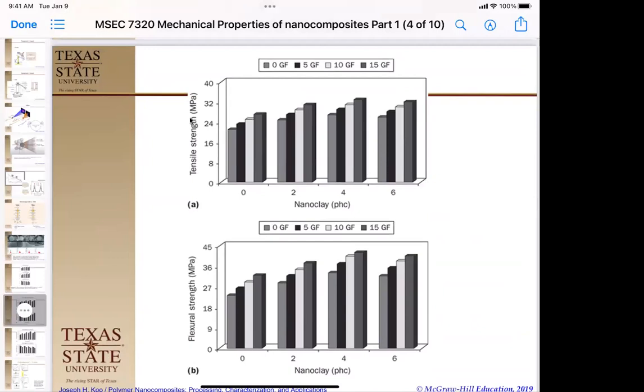So we have these nice platy montmorillonite with glass fiber in our system, and we see as we increase the loading of the clay in parts per 100 right here, we see that, oh, it's getting a little bit stronger. And if we include the top one, this is 0 glass fiber, 5, 10, and 15. This is no polymer, no clay, 2 parts per 100, 4 parts per 100, and 6 parts per 100. So you're like, okay, initially, just adding glass fiber increases the tensile strength. Okay, that's a good result, right?